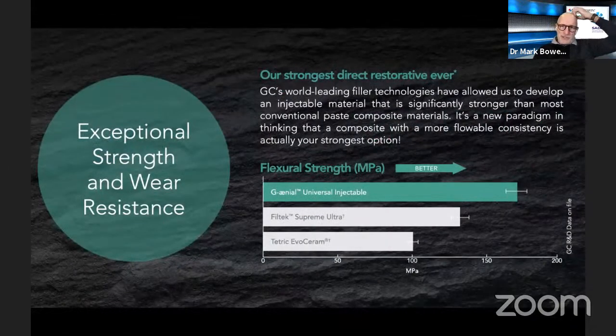And really what makes this product unique, and what amazed me, is that when injectables came on the market, I think that as dentists, we've been taught over the years that any flowable composite will definitely have weaker physical properties than normal syringe nano type composites. But as you see, this is not the case. We compare the G-aenial Universal Injectable, looking at flexural strength, which is the important one, with 2 really popular nano composites, syringe composites, normal composites that we would use. And you can see that the flexural strength is actually stronger. And so this is a complete paradigm shift in flowable dentistry.